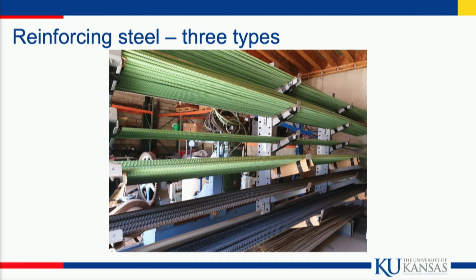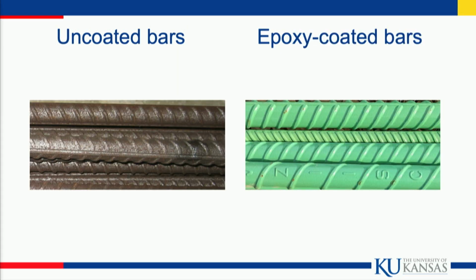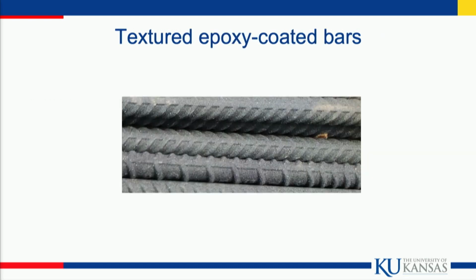So the work we're doing, we're using 3 different kinds of reinforcing bars. On the top, you see epoxy coated. In the middle is regular uncoated conventional reinforcement. At the bottom, coated, it kind of looks like it might be the same as uncoated, but it's a little bit different. Let's take a look. We're all familiar with uncoated bar, and we know what epoxy coated rebar looks like. We're also testing a textured epoxy coated rebar. This has the regular green coating on it and then a texture coating on top. What we know from conventional concrete is that the texture coated bars give the same bond strength as uncoated bars, whereas epoxy coated bars give a lower bond strength. And we want to see if we can get that same higher strength when we're working with UHPC.